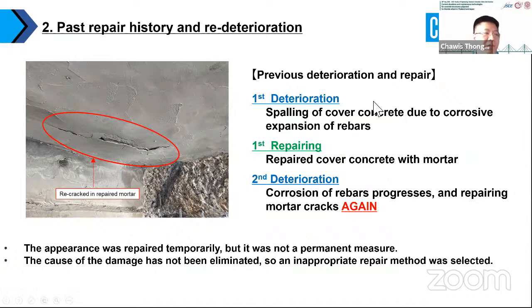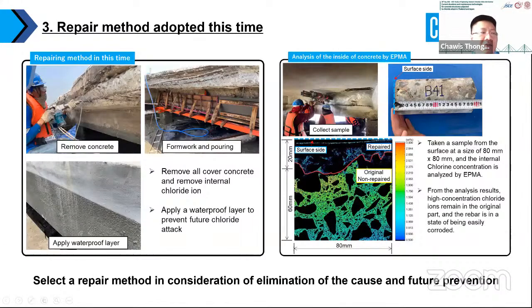Based on our repairing project, we selected the target structure and started to remove not only the concrete surface but also the concrete behind the reinforcing steel inside. We need to remove the chloride around the reinforcing bar as well, to eliminate the cause of deterioration. After the section repair is complete, waterproof material is applied on the entire surface to prevent the intrusion of deterioration factors in the future.